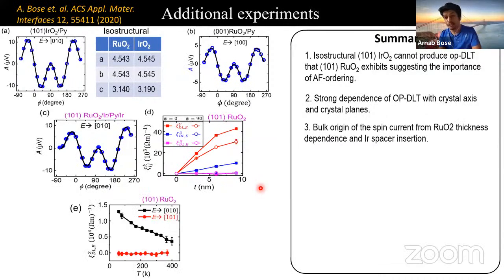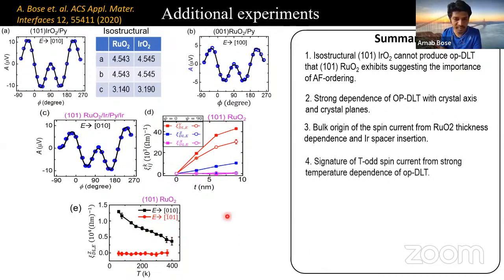So finally, as I mentioned before, temperature dependence measurement could be an indication to know if we have any contribution from the time odd spin current. So we did temperature dependent out of plane anti-damping torque efficiency measurement. We find that in one of the crystal axes, we never observe any extraordinary torque, but in the other crystallographic axis, we always observe it, and that strongly increases as we cool down. It increases nearly by a factor of 3, meaning 200%, as the material is cooled down. So this suggests that we could have a strong contribution from the time odd spin current as well.